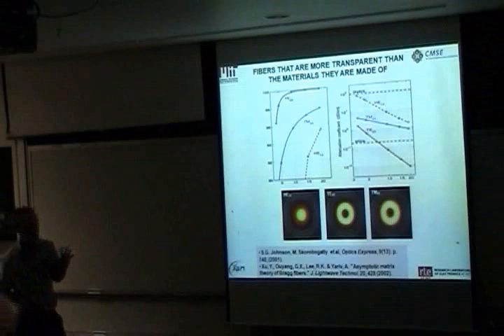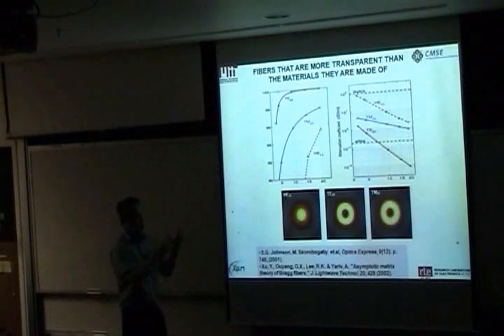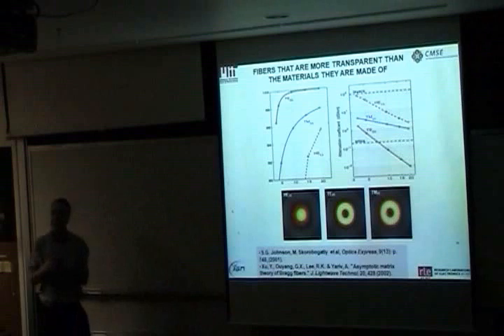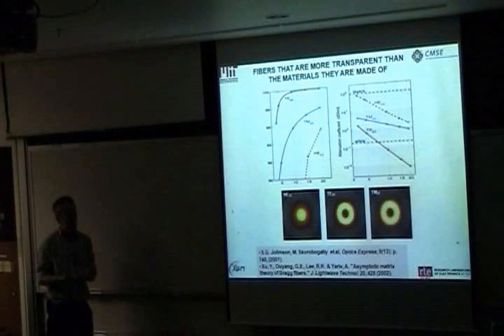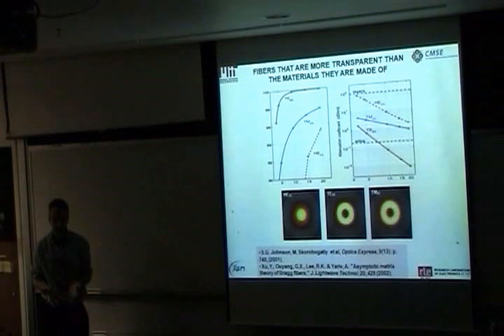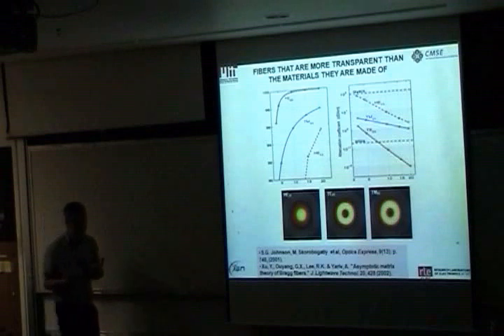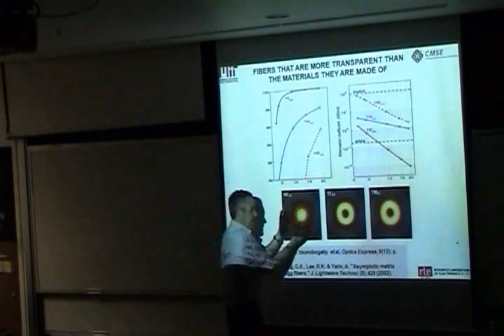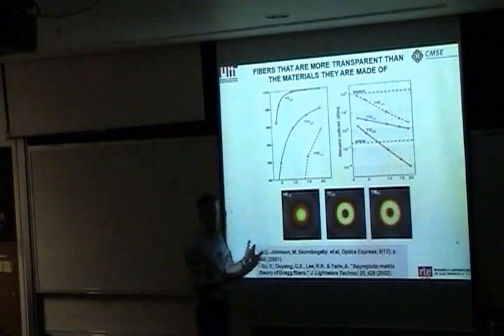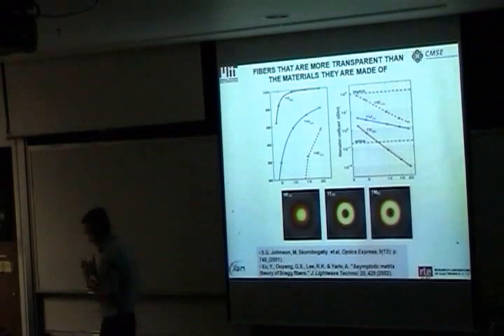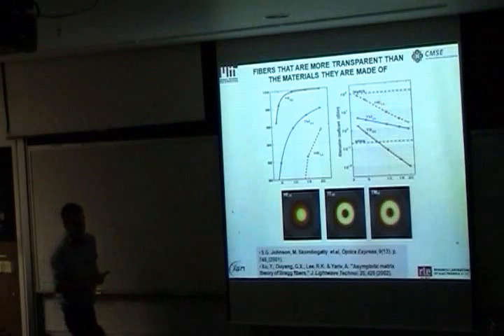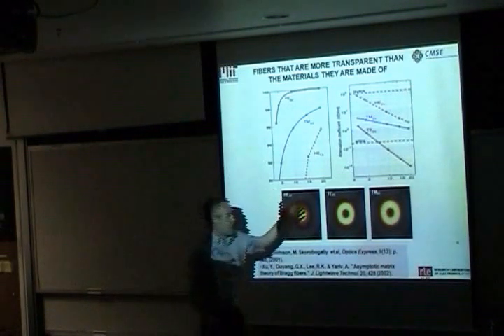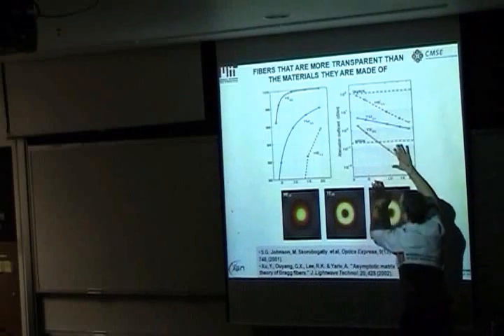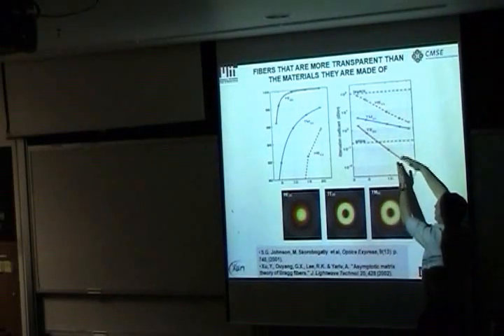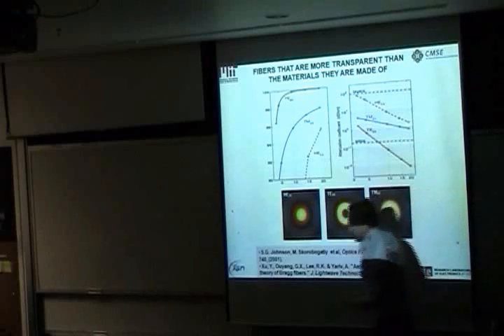So the idea here was quite simple. Up to this point, fibers were always limited by the losses of the material the fibers were made of. You could never make a fiber that is more transparent than the materials it's made of. Why? Because light had to go through the fiber. However, if you could use this mechanism for confining light, light could actually go through a hollow core, and you would then have losses that are much lower than the intrinsic material losses. So these were calculations in which we showed that you could actually have a fiber that has much lower transmission losses than its constituent materials.